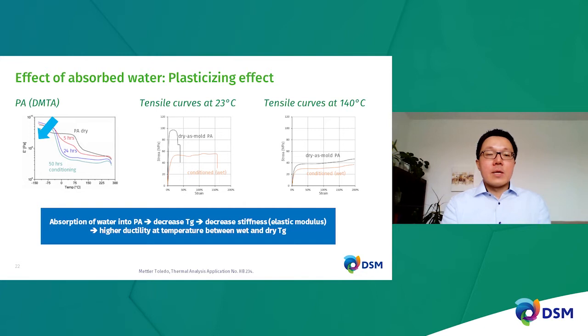Here, I want to highlight a bit more the consequence of having absorbed chemicals, in this case water in polymer. The left-hand side figure shows the stiffness as a function of temperature of polyamide in dry conditions and in wet conditions. The wet conditions are polyamide that has been placed in a humidity chamber for 5, 24, and 50 hours. You can see that the glass transition temperature of polyamide, shown as the first order reduction in the stiffness, for dry polyamide, the Tg is around 75 degrees Celsius. When you start to wet the polyamide, the Tg goes dramatically down below 0 degrees Celsius. After 50 hours conditioning, we are talking about a Tg of minus 20 degrees Celsius.